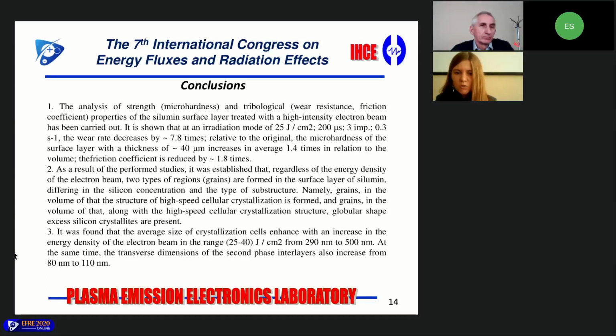And as a result of the performed studies, it was established that regardless of the energy density of the electron beam, 2 types of regions or grains are formed in the surface layer of silumin, differing in the silicon concentration and the type of substructure. Namely, grains in the volume of which the structure of high-speed cellular crystallization is formed, and grains in the volume of which, along with the high-speed cellular crystallization structure, globular silicon crystallites exist.